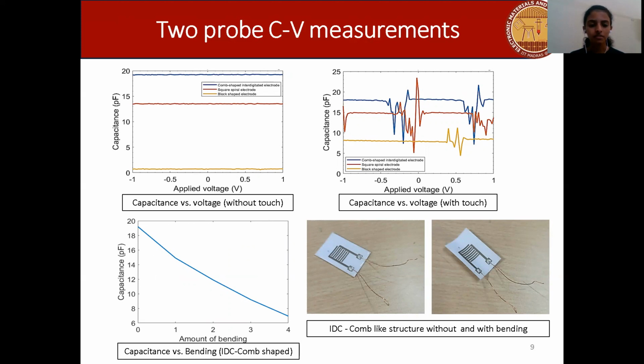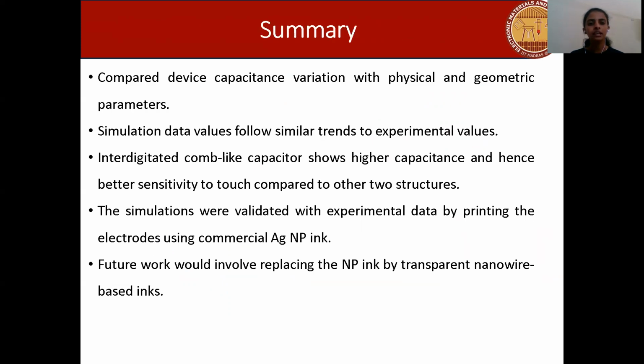I'm also trying to follow up this work by applying a bending force on the remaining 2 structures and see how their capacitance is varying with the bending, and also to observe how the capacitance is varying with other geometric parameters. To summarize, I've compared the device capacitance variation with different physical and geometric parameters of the electrodes, and I've observed that the simulation data values are following similar trends compared to the experimental values. That is, the interdigitated comb-like capacitor was showing a higher capacitance and hence a better sensitivity to touch compared to the other 2 structures.